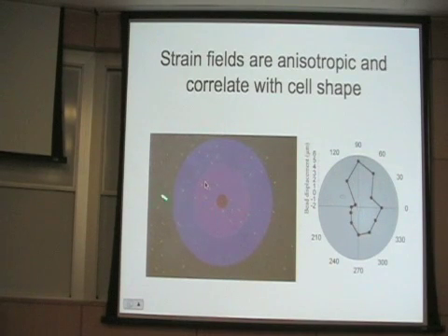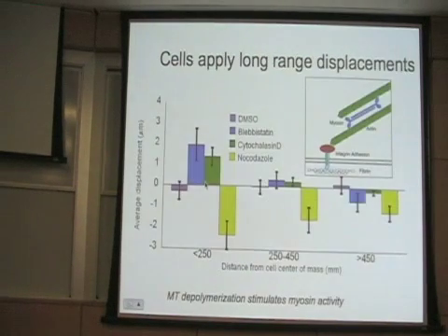Okay, so a lot of these beads have undergone movements, but they undergo movements in an asymmetric way. So in this plot, the farther we are from the origin, the larger this displacement is. The beads will move about 6 microns at the edge of the cell, and there's an asymmetry. If here's the long axis of the cell, beads are moved, and therefore the deformations are larger along the long axis of the cell than along the short axis, but they're really contracting everywhere. And they contract the matrix surprisingly far away.